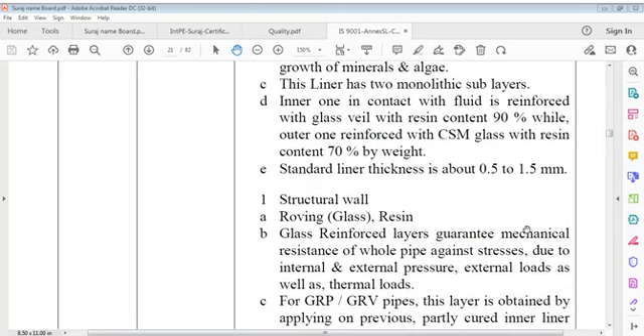This liner has two monolithic sublayers. The inner one, which is in contact with the fluid, is reinforced with glass veil with resin content 90%, while the outer one is reinforced with CSM glass with resin content 70% by weight. Standard liner thickness is about 0.5 to 1.5 mm.